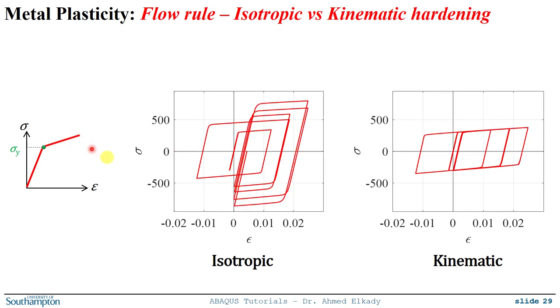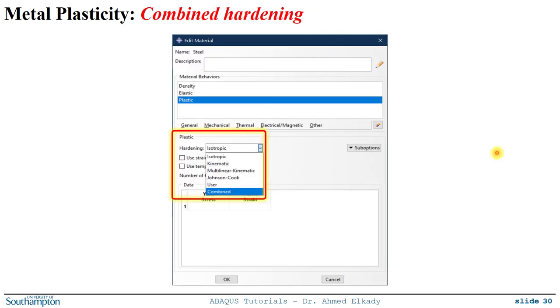However, if you put a hardening slope, you will see now the difference. It becomes evident. So under isotropic, you see the symmetric behavior between the compression side and, let's say, the tension side. And you see, again, the cycles or the size of the yield surface keep getting bigger with accumulated plastic deformations. The kinematic, on the other hand, we see the asymmetric behavior between the compression and tension sides. And we see that the yield surface or the yield range remains constant and doesn't change. So if we are doing modeling or doing some kind of simulation in ABAQUS that involves cyclic hardening, we want to add a combined hardening rule. So we need to see isotropic and kinematic hardening rules taking place in my material behavior, because this captures the actual behavior of the metal, and particularly here I'm talking about steel and its variations.